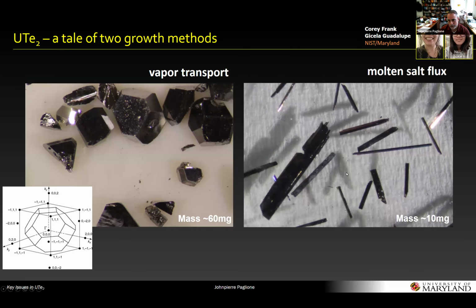And so in fact, if you look at the morphology of the crystals, I think this is quite common. You tend to grow quite large crystals with vapor transport. You can see these nice big crystals here that seem to show nice facets that correspond to the orthorhombic crystal structure. And salt flux tends to give you these more needle-like shaped crystals. So depending on what experiment you're doing, some of these can be advantageous or disadvantageous in just the shape, of course.